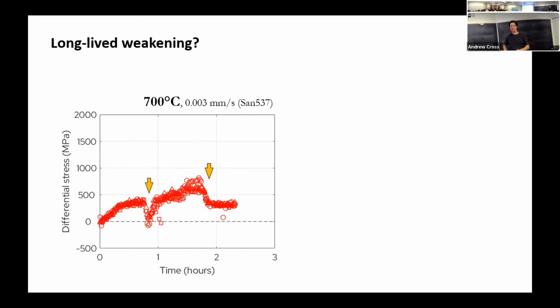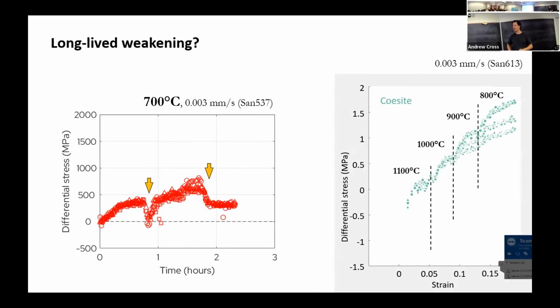And just to prove that we're not totally crazy here, I had our overnight shift people on that overnight shift last night run an experiment where we just formed coesite and then we deformed it at a constant rate, but we did a series of temperature steps. So in this case, we're going down in temperature and we're getting strengthening. So this is what we expect to see, but we're seeing the opposite in the transformation experiments. So something about the phase transition is actually causing the sample to weaken as it goes to lower temperature.